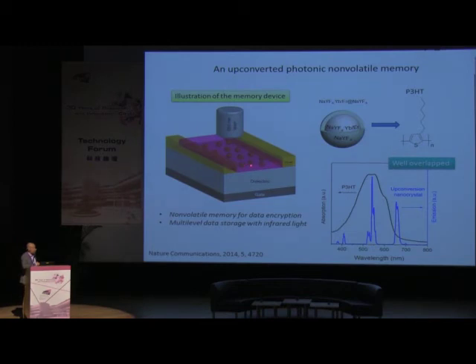And the emission is in the green region, as you see, which perfectly overlaps with the polymer. So the polymer basically reabsorbs that emission from the nanocrystals. So it creates more excitons. At the end, you apply a voltage to have more charges that you can play around with. It means basically the light gives you more charges. Now, we also did some of the work that I have tried to present with quantum dots.